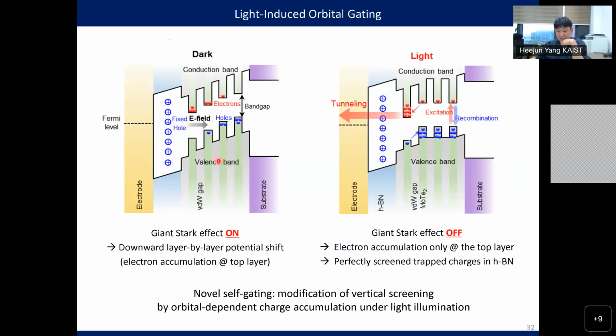Anyway, the schematic is like this. We have some momentum-dependent or orbital-dependent built-in potential like this, electron accumulation. This is the vertical screening. And if we illuminate light, we have a built-in potential for K-valley electrons. So we have this accumulation here. And then they make some tunneling current through hBN. So we can gate only the top MoTe2 layer separately from the bottom 3 layers. This is called the giant Stark effect because we have level splitting by charge displacement. And then we can turn off the last 3 layers. Okay. So this is the result.